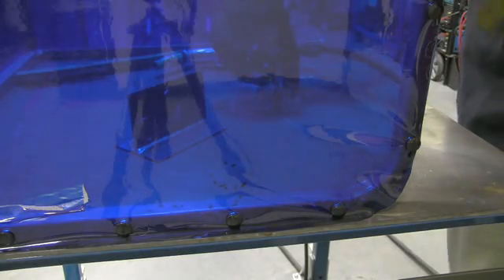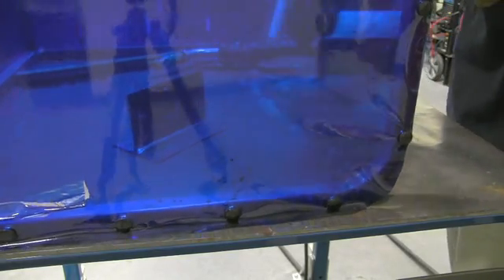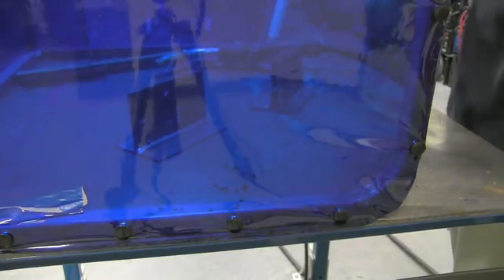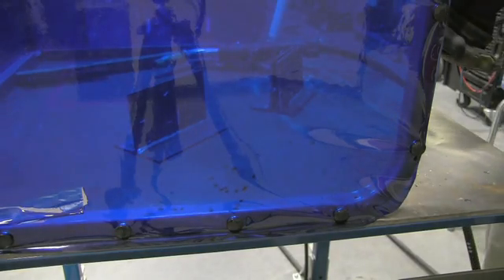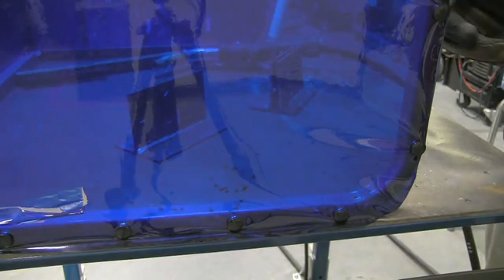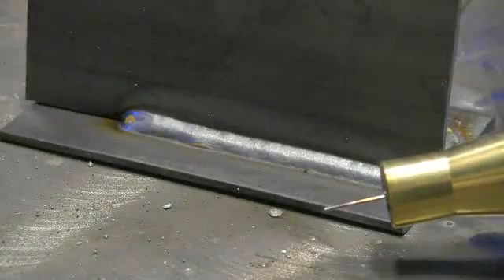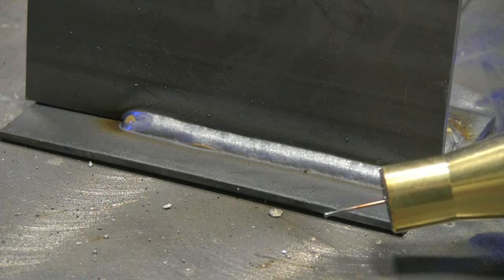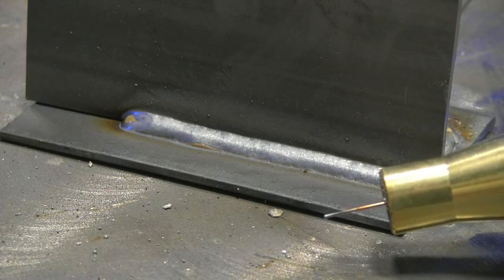Okay, so after that, I can see that the weld generated very little spatter and the welding arc was very consistent, and that was 16 volts at 200 inches per minute. So here's the finished product. You can see that the weld has a nice smooth profile and there is very little spatter generated.